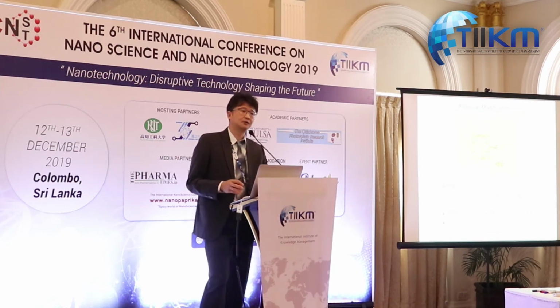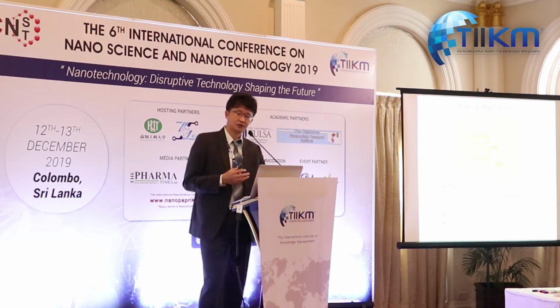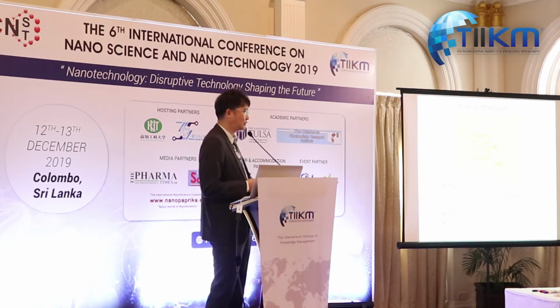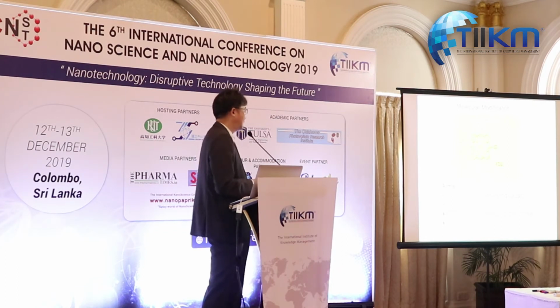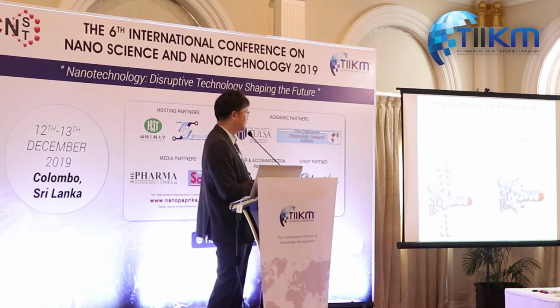So we next try to modify the molecular structure based on YD2 with the aim of improving the light harvesting capability, in other words, achieving red shifted and broadened absorption. At the same time, we have to reduce dye aggregation and charge recombination rate, and also increase the long-term stability. So we modify the donor, the meso-phenyl, and the acceptor. Here's the structure of YD2. The tert-butyl groups at the meta position of the phenyl are not bulky enough to completely suppress dye aggregation.